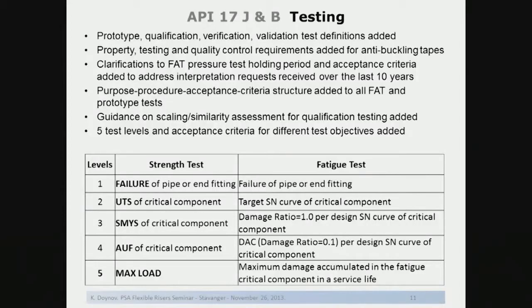For example, here, every single strength test can be tested either to failure of the pipe or the end fitting. The second level is to the ultimate tensile strength of the critical component. The third level is to the yield strength of the same component. The fourth level is up to the utilization factor per 17J table 6. And the last one is to the maximum load. And the logic is that if you test at the lower level, you're going to automatically cover the objectives of the higher levels.